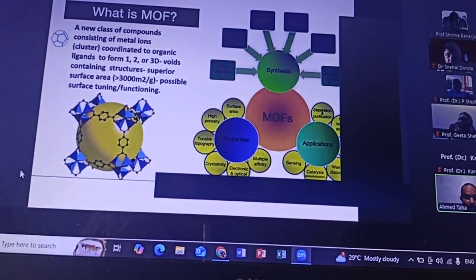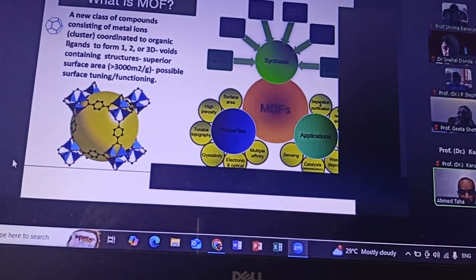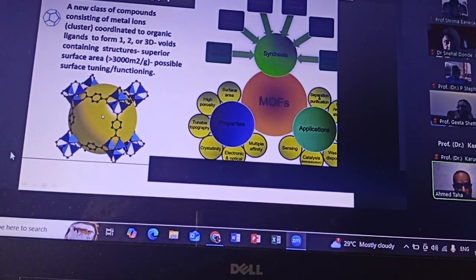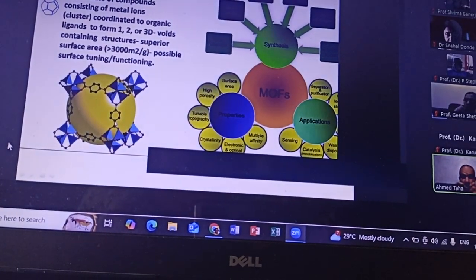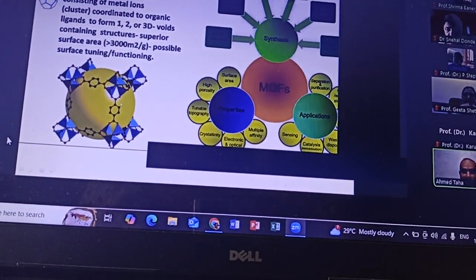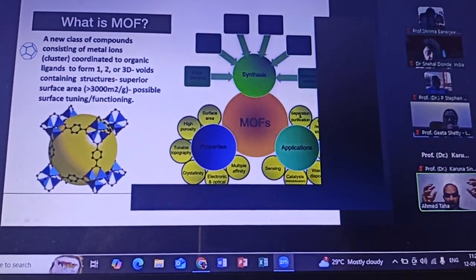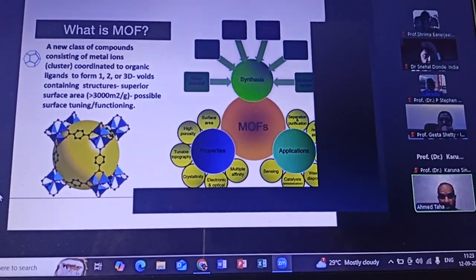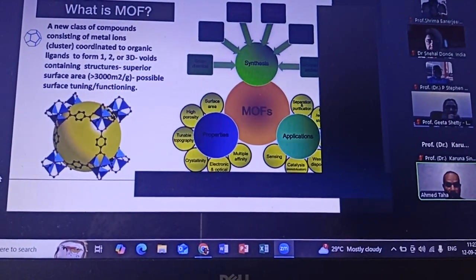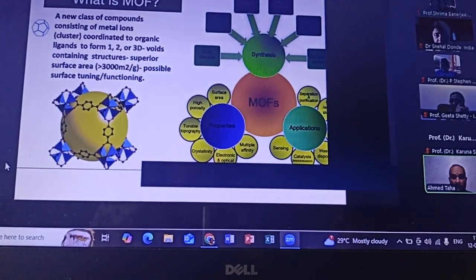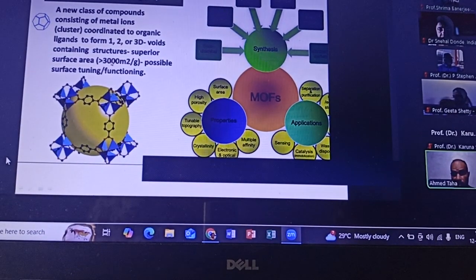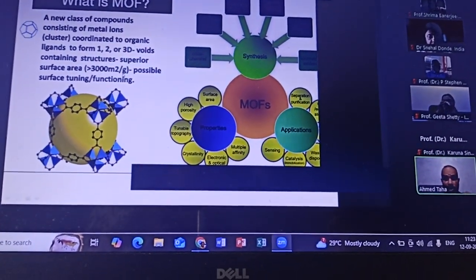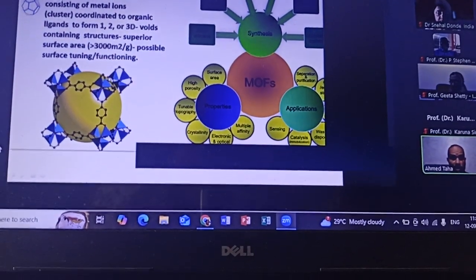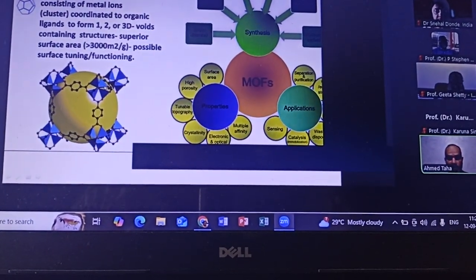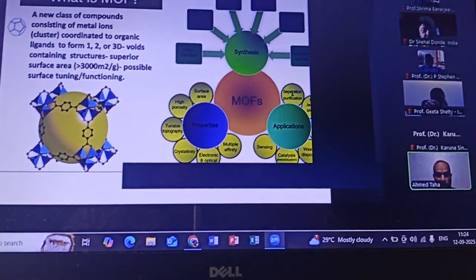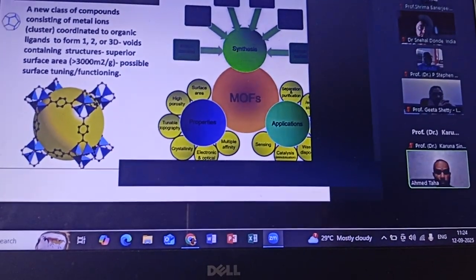One of the most emerging materials is metal organic frameworks, and simply this material is composed of two main things: organic linkers linking metal nodes. So these metals are linked together with organics, making a void. This structure gives us very unique properties of extremely high surface area. It can reach more than 3,000 square meters for each gram of this material, and you can also modify it, add functional groups or change functional groups, so it's tunable to the application you need.